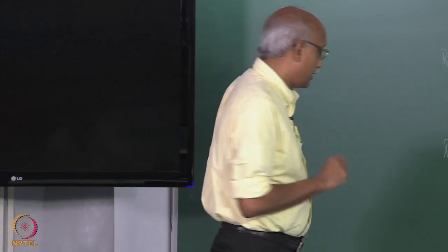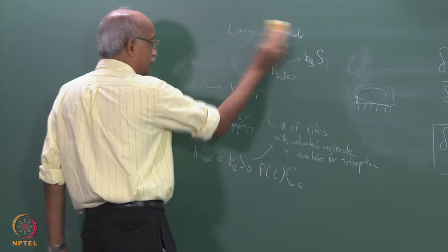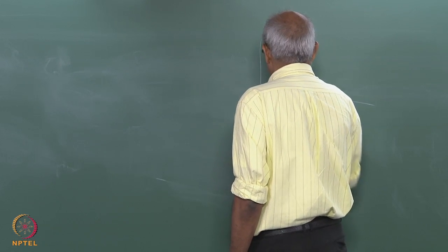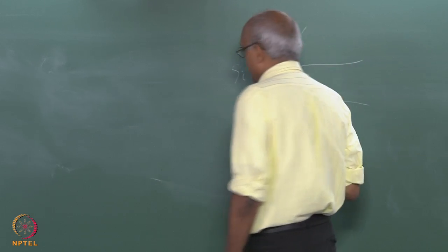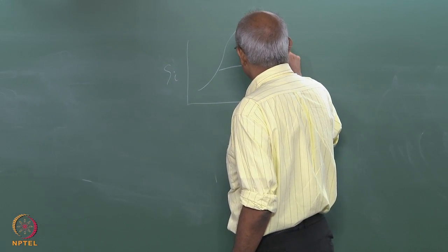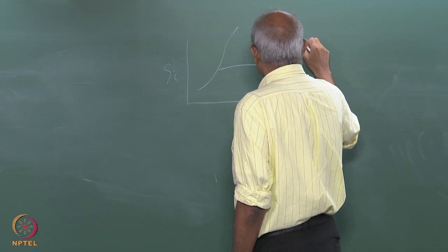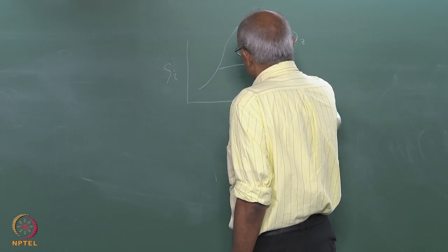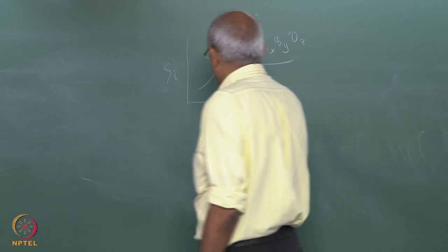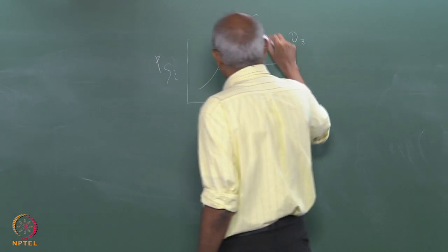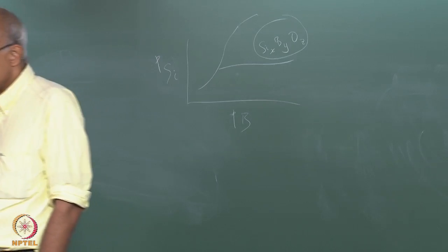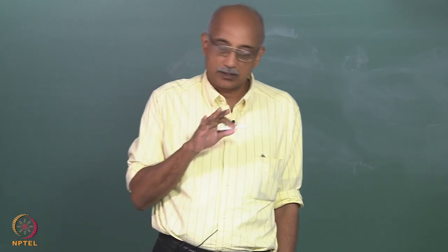In all these systems, again, you start with the analysis of the phase diagram. For example, if you are incorporating boron in silicon, you should have some picture of what the phase diagram is going to look like. Supposing you are trying to form a borosilicate, you have to know what concentration ranges or partial pressure ranges of B and Si you have to be at for this film to be even thermodynamically viable. And then you try to set your thermodynamics of the system so that you operate in the viability range.